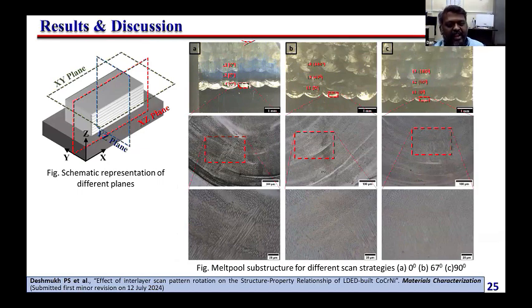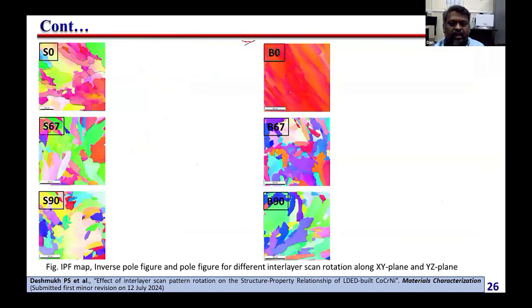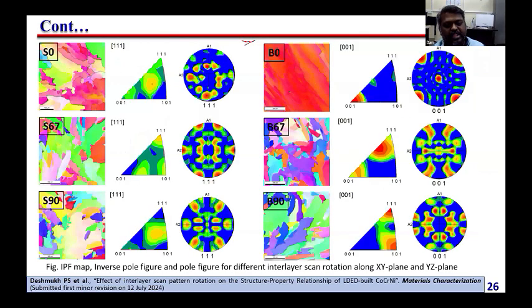Our main objective is how we can reduce this epitaxial grain growth. Even in the substructure we observe too much epitaxial grain growth. So when we did this 0, 90 and 67, we understood that the middle one, the 67-degree, is giving a very fine structure compared to 0 and 90-degree. We did multiple images and tried to measure this substructure. We understood that the finer structure we got is in the 67 degree, and also the epitaxial growth is suppressed or reduced in the 67 degree scan rotation.